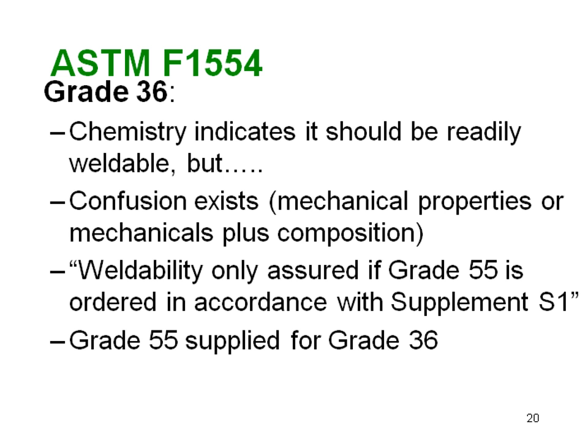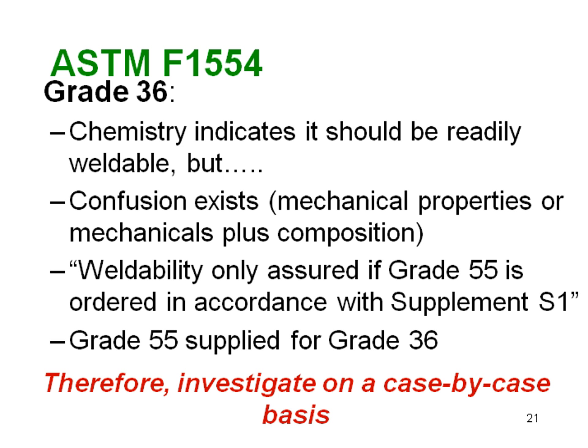The conclusion I come to is I'm going to need to investigate on a case-by-case basis the weldability if I have 1554 grade 36. Now, that doesn't mean it's always going to be bad. You randomly may have material that was low enough in carbon, low enough in alloy that makes a good weldable material. But you're going to have to investigate because I don't think you can assume it's guaranteed.